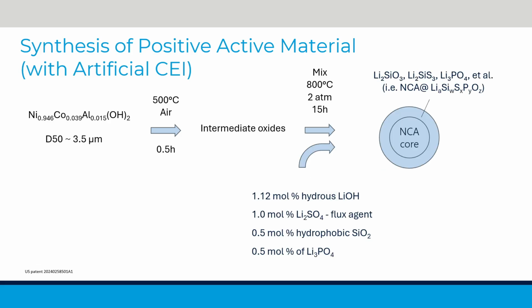In the second step, a mixture of chemicals is added into the intermediate oxides, including 1.1 equivalent of lithium hydroxide, 1 molar % of lithium sulfate as a flux agent, half molar % of hydrophobic silica, and half molar % of lithium phosphate. The mixed material is heated at 800 degrees Celsius under 2 atmospheres for 15 hours. Single particles of NCA cathode with silicon, sulfur, phosphorus coating are obtained.